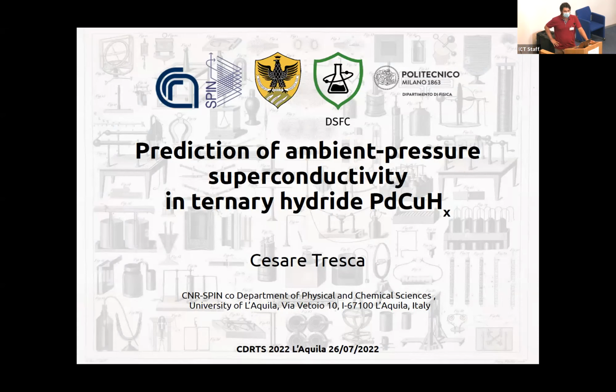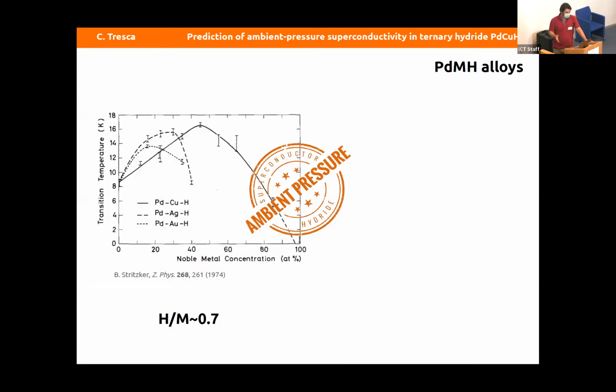Good evening, I'm Cesare Tresca from CNR SPIN. I speak about the prediction of ambient pressure superconductivity in ternary palladium copper hydrides. Also in this case, we try to lower the pressure needed to superconduct. We start from an experiment performed in 1974, in which Stritzker, alloying palladium hydride with noble metals, registered an increase of the superconducting critical temperature up to the maximum in palladium copper hydride, in which the superconducting critical temperature was double with respect to palladium hydride, with a concentration of 50% and a hydrogen on metal ratio of about 0.7. We are speaking about ambient pressure superconductivity.